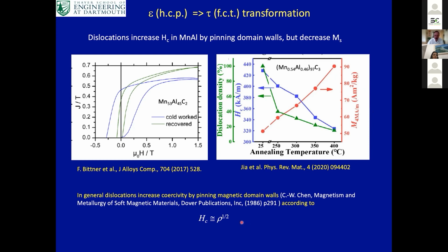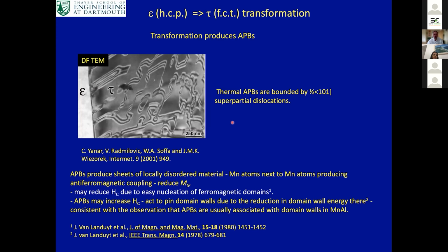And in general, of course, in magnetic materials, the coercivity is roughly proportional to the dislocation density to the power 1/2. The transformation also produces thermal antiphase boundaries, as shown here. With thermal antiphase boundaries, because there's a mismatch in the interface, you again have manganese atoms sitting next to manganese atoms. And so you'll have some antiferromagnetic coupling there, reducing the saturation magnetization. But at this point, it's not quite clear what these do in terms of the coercivity.